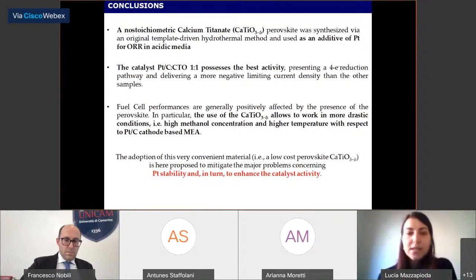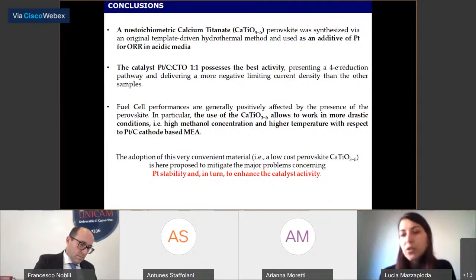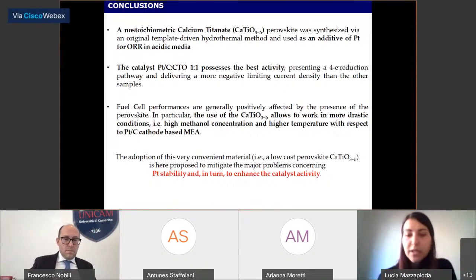And the presence of this perovskite has allowed to work in more demanding conditions, which are high methanol concentration and a higher temperature with respect to a platinum-carbon cathode. I'd like to stress that the adoption of this very low-cost material has improved the platinum stability, but especially was able to enhance the platinum catalytic activity towards the ORR reaction of interest.